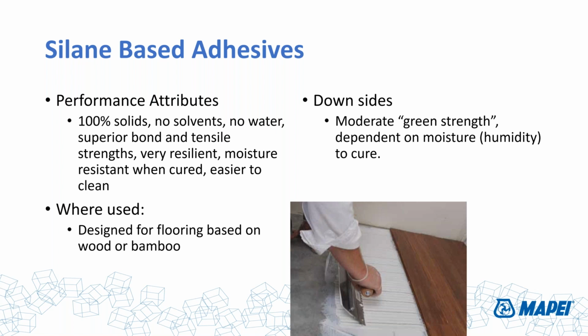The challenge with bonding bamboo is that it has a non-porous back. The backing is coated just like the top, so you're trying to bond to a non-porous substrate. So there's no way for urethane, for example, to off-gas its CO2 into the open wood. You're sticking to a piece of plastic. MS adhesives don't off-gas, and that makes them a little bit easier for use in that area.